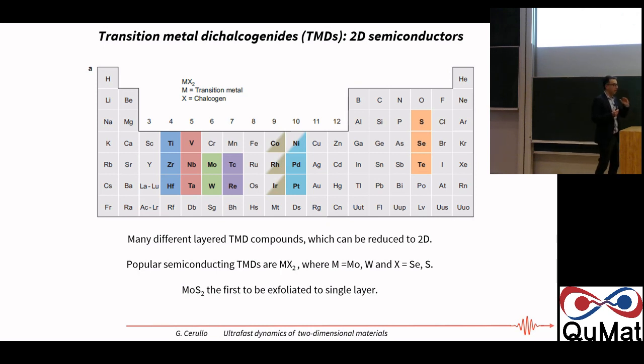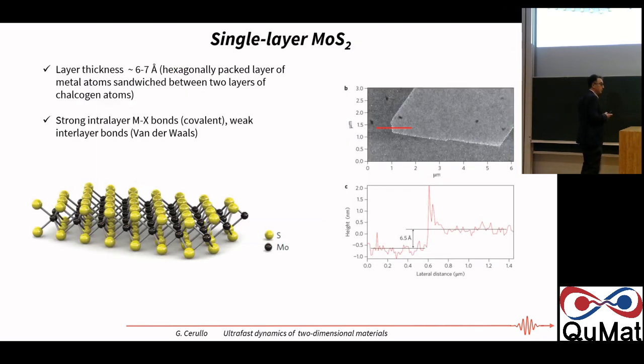So they consist of a layer of strongly covalently bound atoms, which is then held together with the other layers by van der Waals force. So they can be easily exfoliated down to a single layer. Now, the prototypical material is really molybdenum disulfide. Here I'm showing you a single layer.